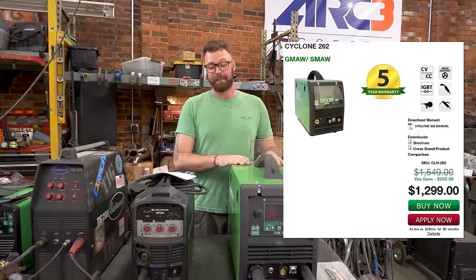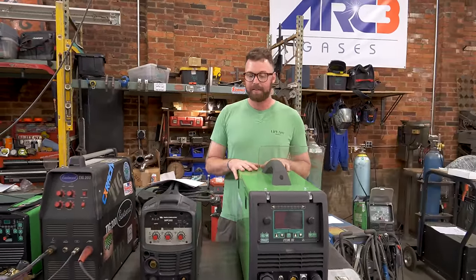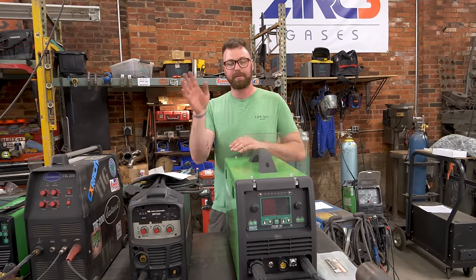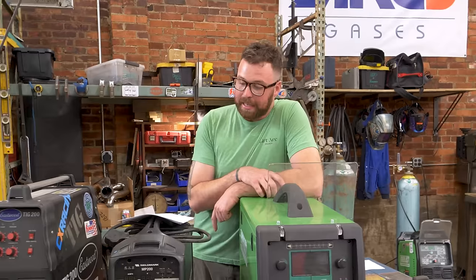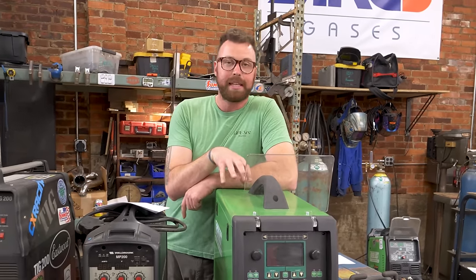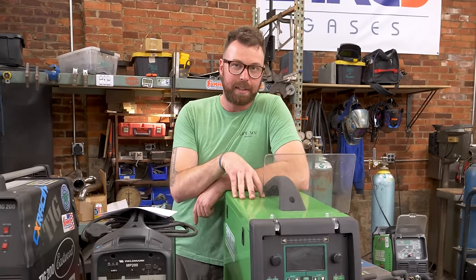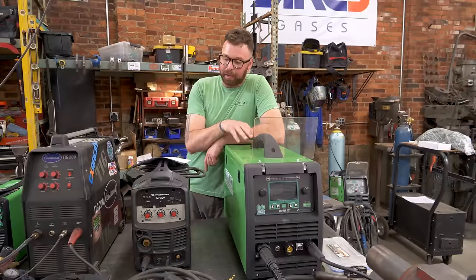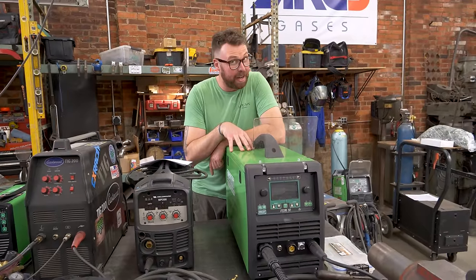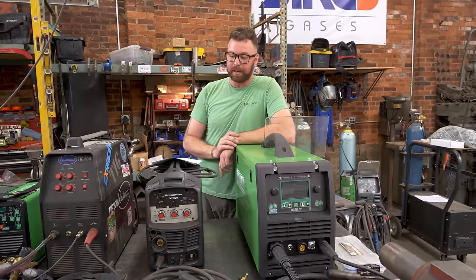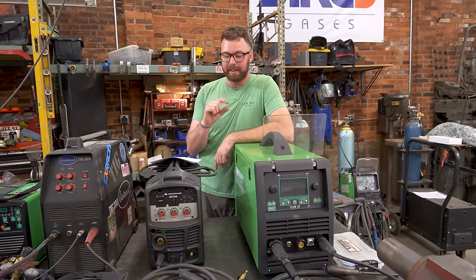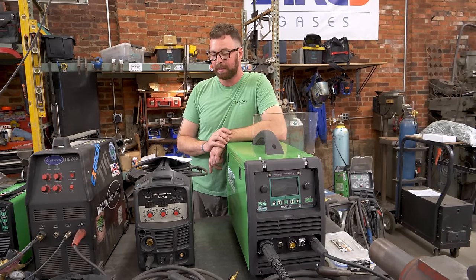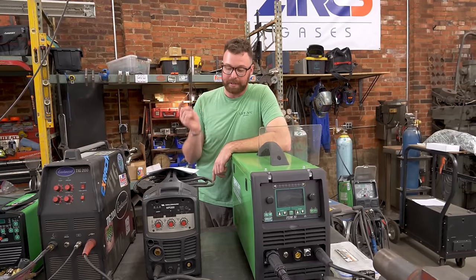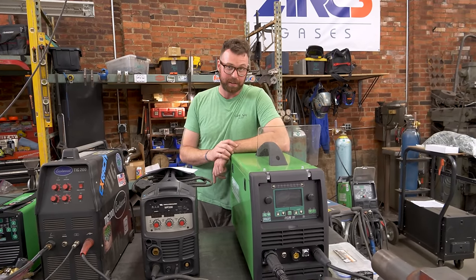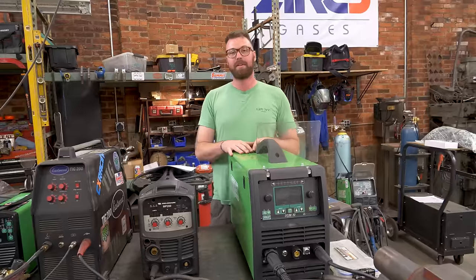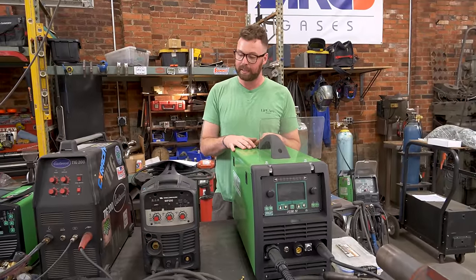So we're getting up there now. This is a serious investment now for most, you know, small form welding shops. It is a 220 volt only machine. So you are not getting 110 volt capabilities anymore. It has a 30 amp to 275 amp range, and you can MIG weld up to 7/16 thick single pass on steel, which is almost a half of an inch. And you can go down to a minimum of 24 gauge steel. So big range there of wire fed welding thickness on steel.